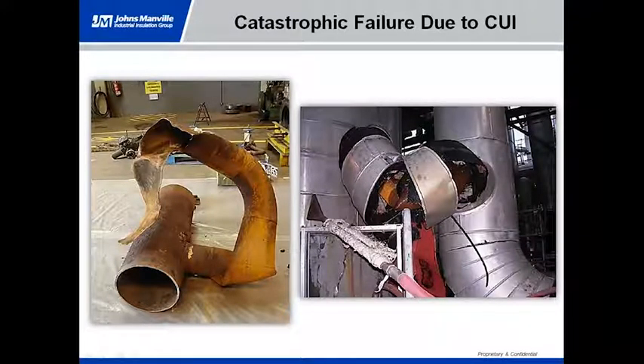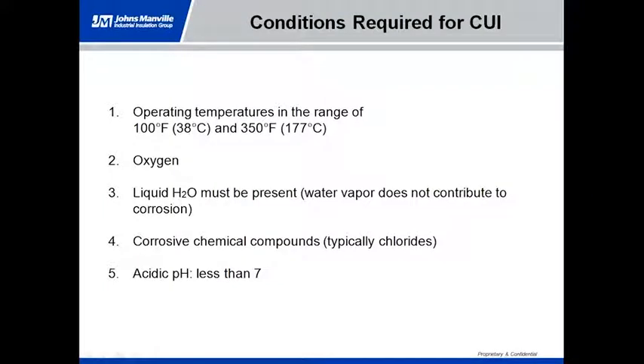It's usually exposed through either sudden storms, improper storage, improper installation, damage to the jacketing, or damage to the lagging. All the above can allow moisture to penetrate into the system. Now, all these scenarios create a potential situation for corrosion under the insulation, and the results can be catastrophic, and we see that in these pictures here, where things corrode to the extent where things rupture and actually can create some very significant damage, not to mention downtime.